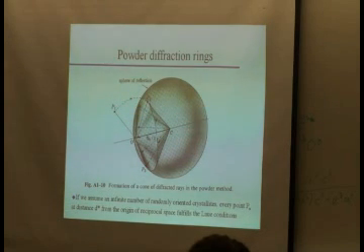Most powder diffractionists don't put their powders on a single crystal diffractometer. They would rather put it on a powder diffractometer, and because we know that this is happening, all that we do is we scan along one dimension, okay? Because we say it doesn't matter whether I measure that ring here or there or there. It really doesn't matter. All I have to do is go through that ring. So that's why we can do one-dimensional measurements in powder diffraction, because it doesn't matter where we measure as long as we measure all the distances from the origin of reciprocal space. That's the only requirement. So, you can even explain what your data looks like by understanding reciprocal space. As I said, this is a very important concept. Okay.